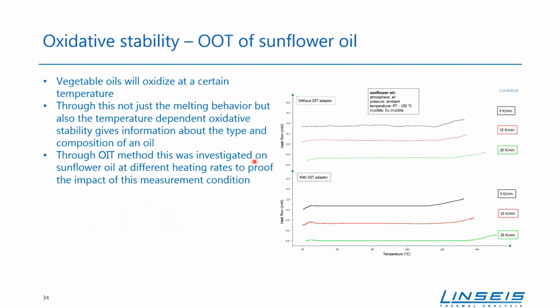So here's now a comparison just for sunflower oil at different heating rates. I performed this test with 5 Kelvin per minute, 10 Kelvin per minute, and 20 Kelvin per minute, on one hand without our OIT adapter, and on the other hand with our OIT adapter. What we can see is that with the OIT adapter, the signal is much clearer. Of course, all of them will oxidize at a certain temperature, and this temperature is dependent on the heating rate because, as I mentioned, we were using ambient pressure here. So the pressure is the same. At the same heating rate, the onset should also be the same, and it is. But with our OIT adapter, the signal is much clearer, and there's not so much noise on our signal, so it's much easier to investigate. This is what we can see here.